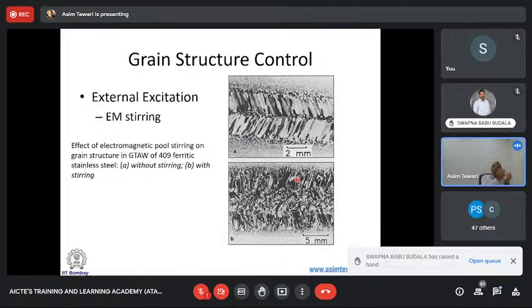And that micro model will essentially lead to some specific changes which you can cause at the melt pool level, which will lead to better microstructures. Whereas at a macro level, the strategies by which you add material, the hatching strategies, will lead to lower residual stresses. So you are actually, in a sense, controlling the additive manufacturing process at two levels. At the macro level, the energy deposition and deposition strategies lead to changes in residual stresses. And then some handles, for instance, like EM stirring, lead to microstructural changes.